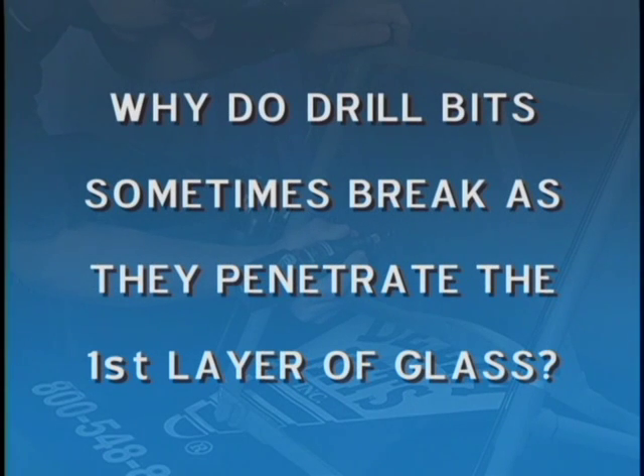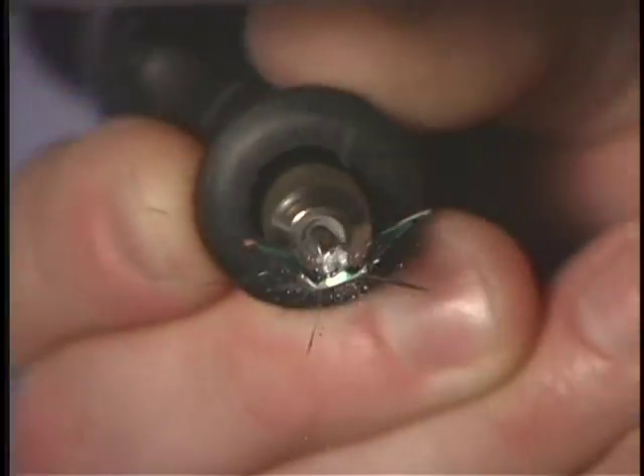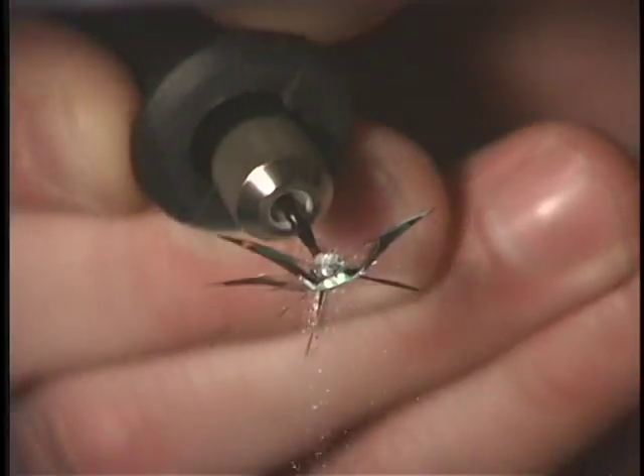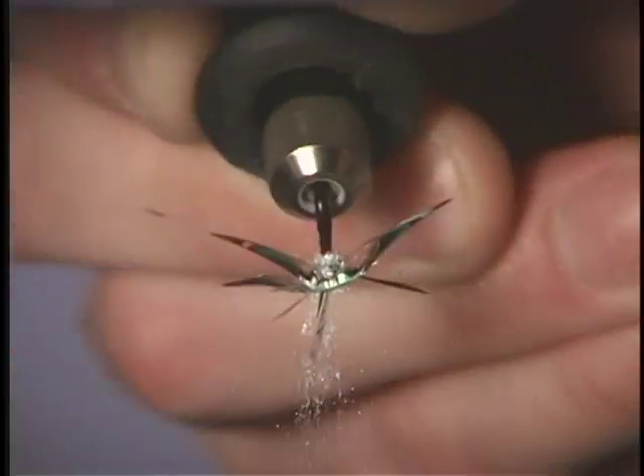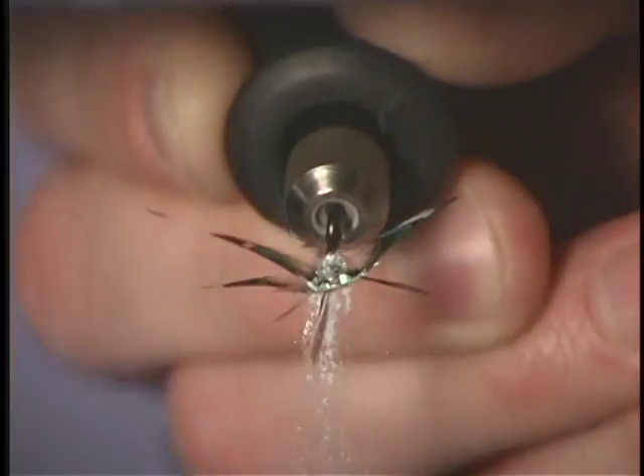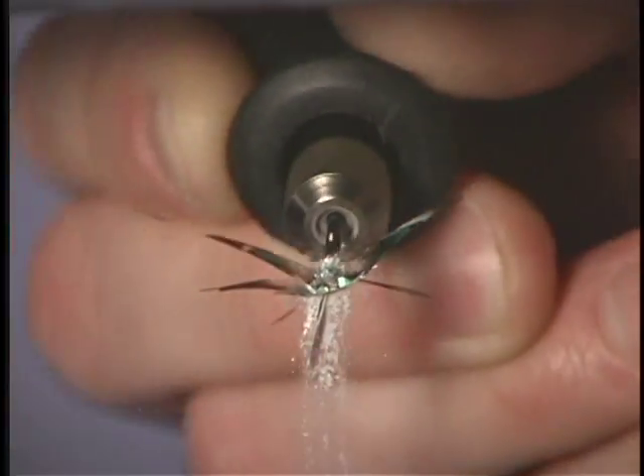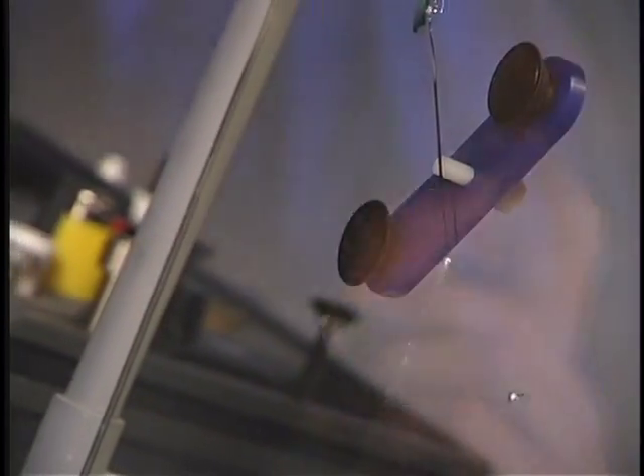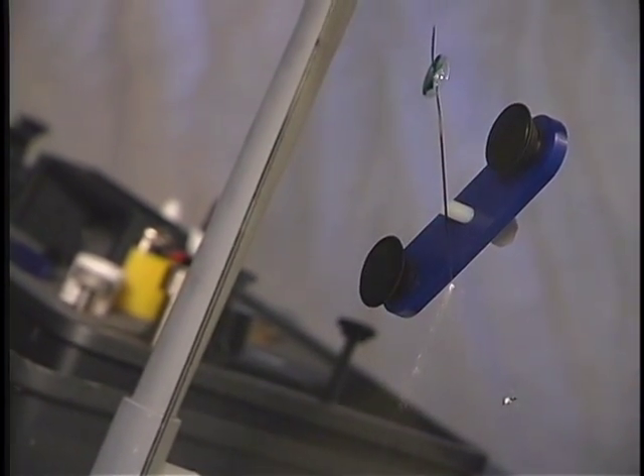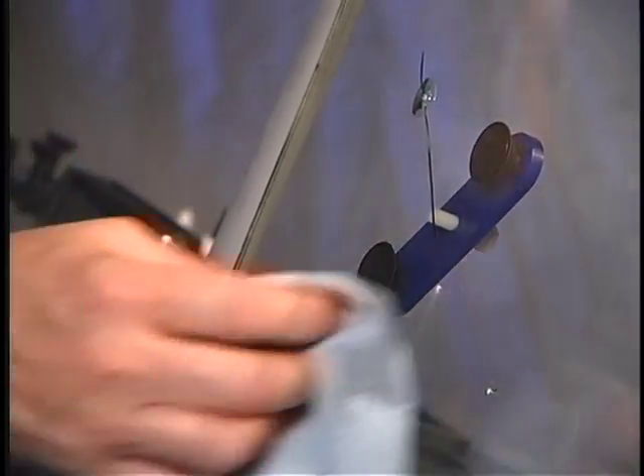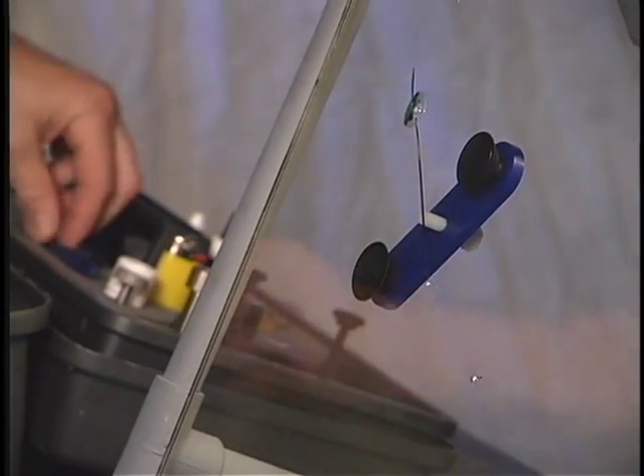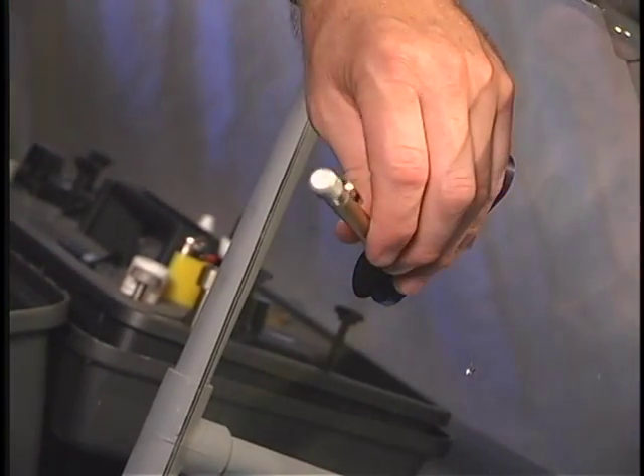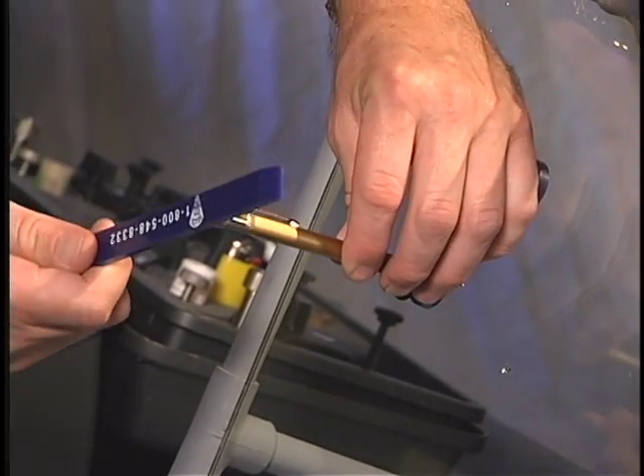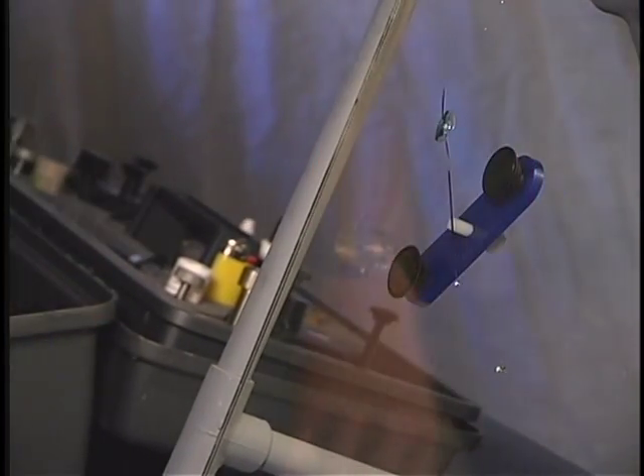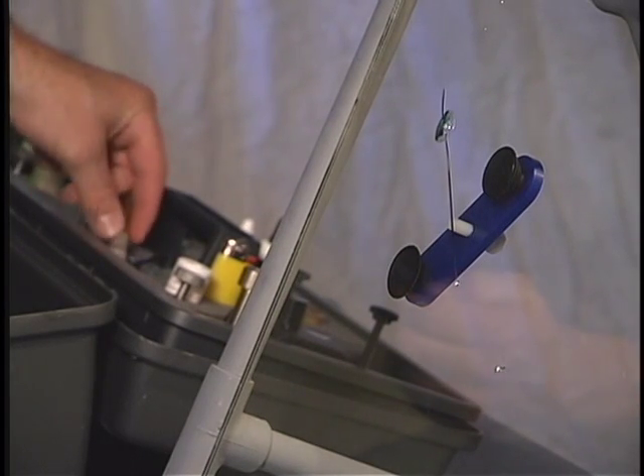Why do drill bits sometimes break just as they penetrate the first layer of glass? When drilling, you should always rotate your drill in a circular motion. This not only helps reduce bit breakage, but will also shape the hole in such a way that air bubbles are easier to remove. Another solution is to drill halfway through the outer layer of glass, then insert a thin probe into the break and tap lightly with a suction cup removal tool. A very small bullseye will be created at the bottom of the drill hole and will not damage the laminate. This procedure is also very effective for stopping long cracks.